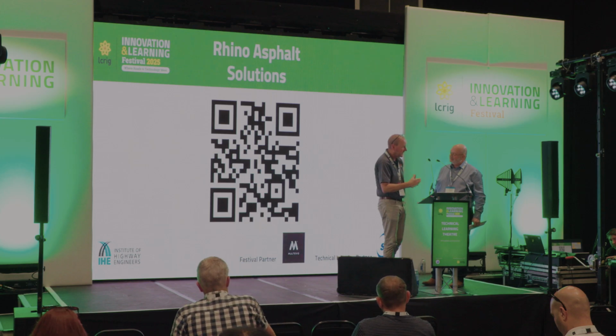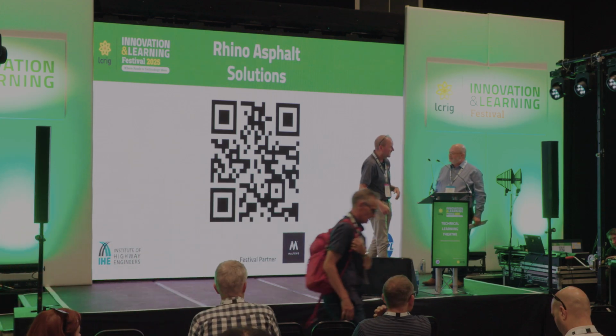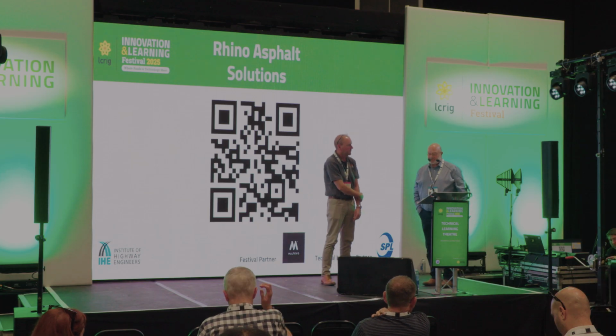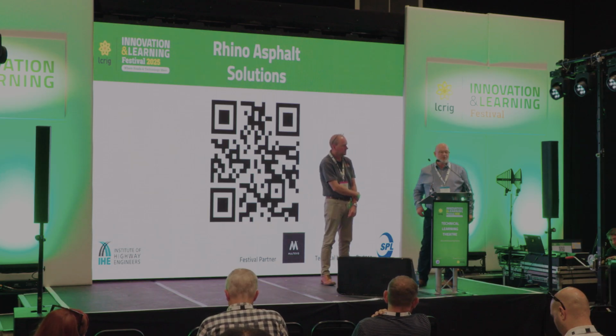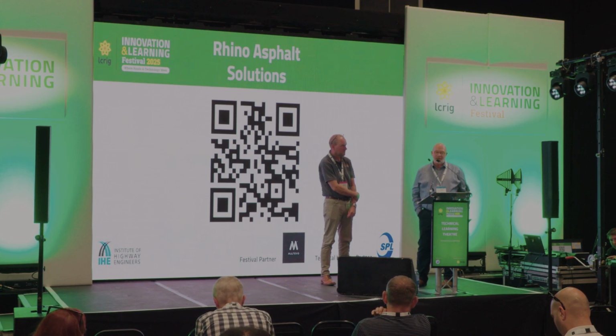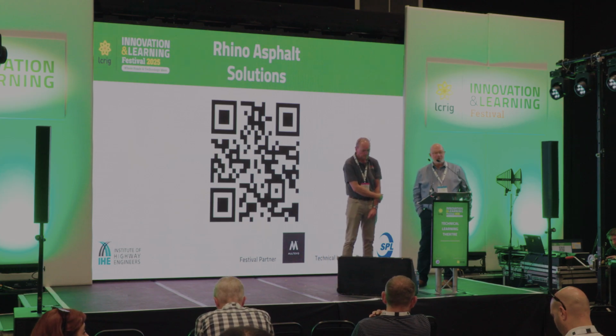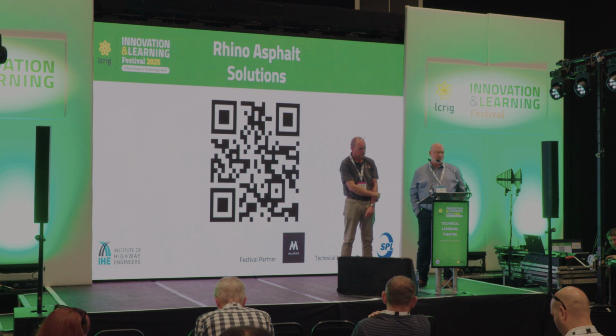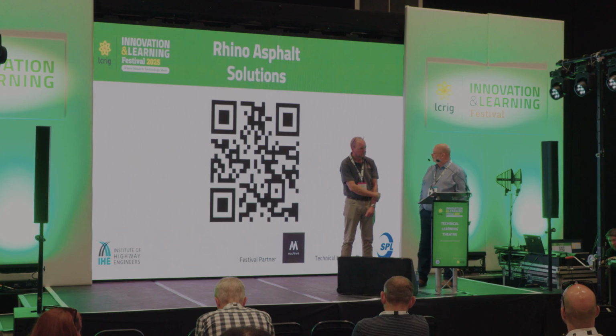Yep. Is there anything you can tell us about your products that might solve that? Yes, certainly. A crack repair is very much a targeted response to a surface defect. And the inlay repairs could be of any width and any depth, so typically they may be 200 to 300 millimeters wide. We do have other materials which are screed applied surface materials. Those have a use. However, being a very thin layer, I would question whether they will effectively repair the crack long term, with the movement that's likely to occur.